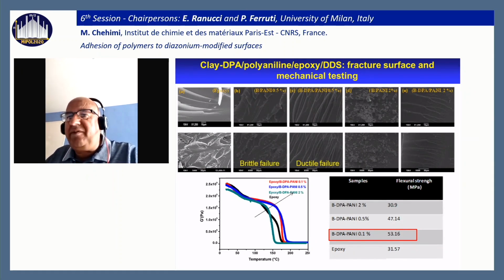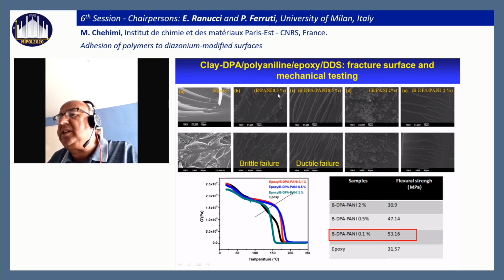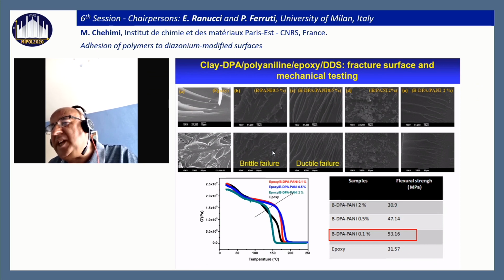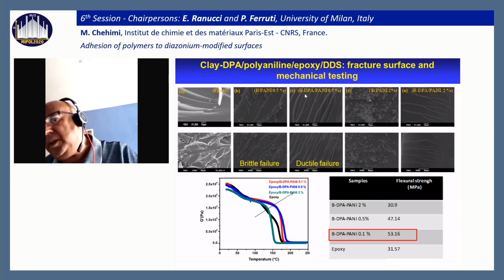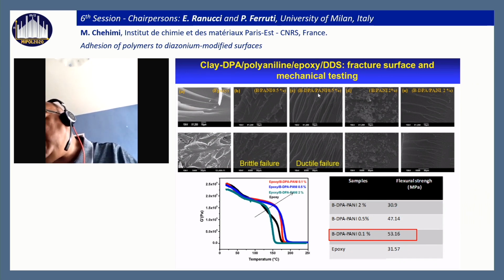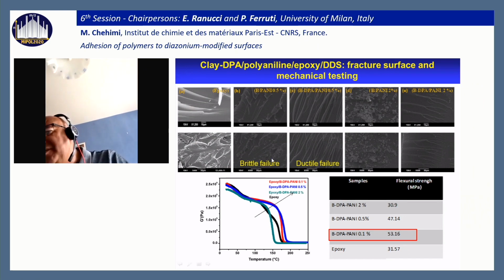Interestingly, when we see the fracture surface of the composites, this is the epoxy and the fracture surface. We also monitored the mass loading of the filler in the epoxy, and we can distinguish between the epoxy nanocomposites prepared in the absence of diazonium salts, and in the presence of diazonium salts used to make exfoliated clay polyaniline nanofiller.